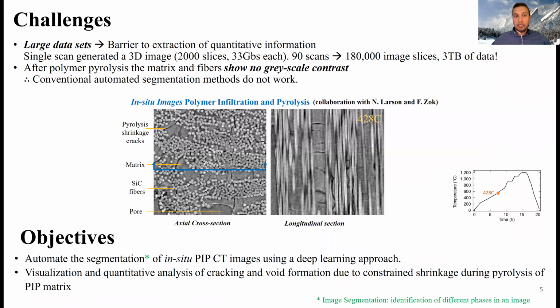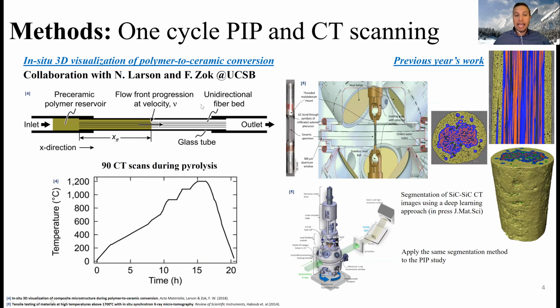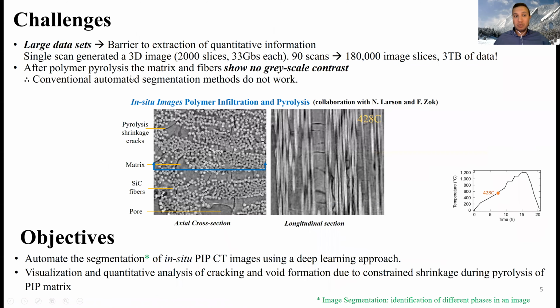So the challenges of these images that were provided by Natalie was that these are images taken across 20 hours with 90 CT scans, and one CT scan generates a 3D image of 2,000 slices. So if you do the math, 90 CT scans is about 180,000 images. That is 3 terabytes of data that you have to go through to analyze and just even visualize this data. So this is a challenge to the extraction of quantitative information.